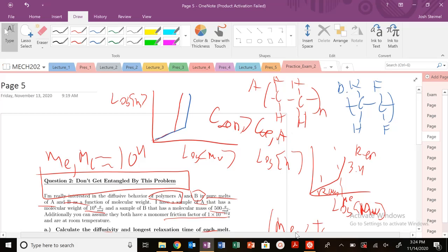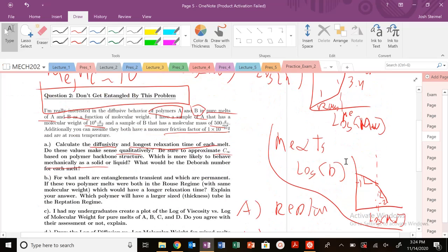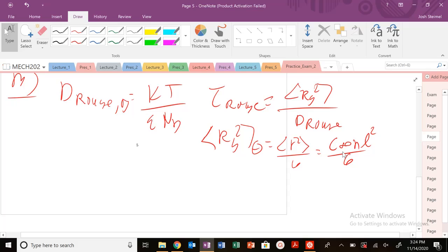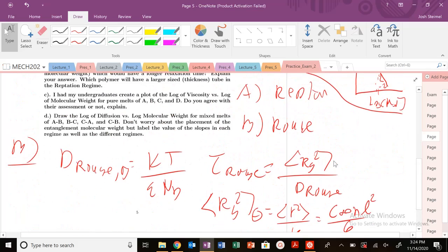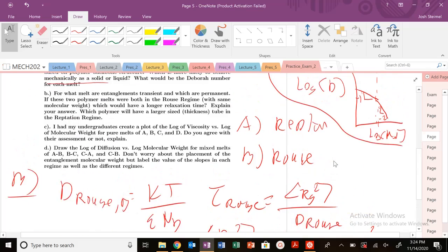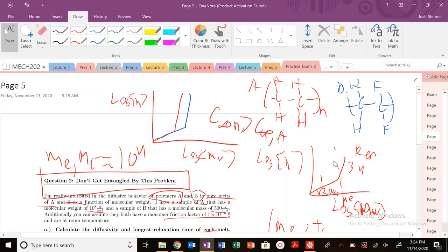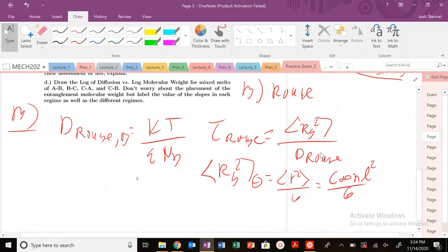The other question we have is, what is our L? What is our monomer, that repeat unit, my monomer length? Well, remember, we could approximate that as just our carbon-carbon saturated bond length. So L for this problem, since we know both of those bonds are 1.54 times 10 to the minus 10, so 1.54 angstroms.